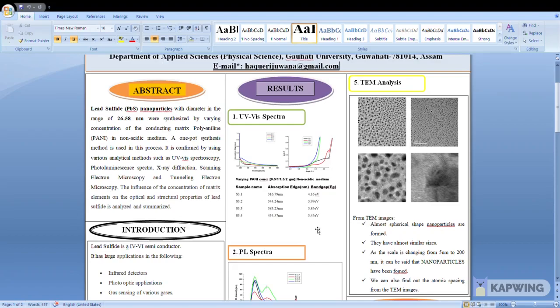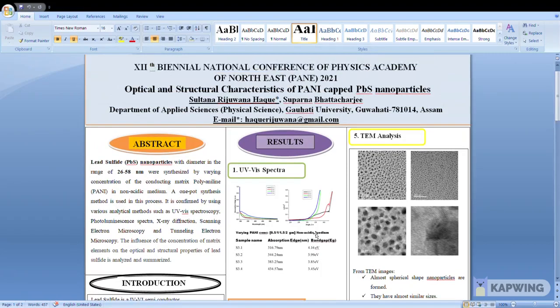Comparing among the 5 samples, we can conclude that with increasing concentration of the matrix element, the band gap decreases up to sample 3. Then it increases for sample 5.